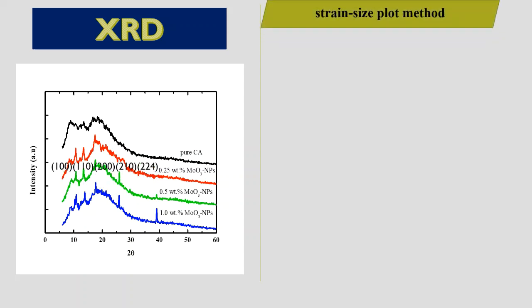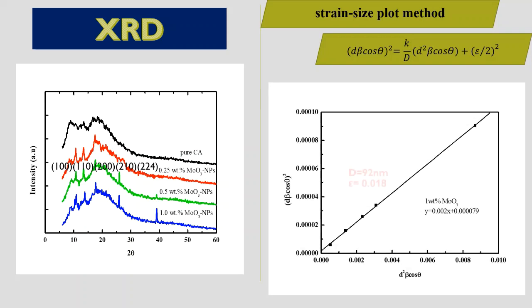We use the strain size plot method to calculate the metal oxide size, by drawing a relation between d square beta cosine theta and d beta cosine theta square. From the slope we get the particle size, which is 92 nanometers, which indicates that the molybdenum trioxide is in nano size after we put it in the film.